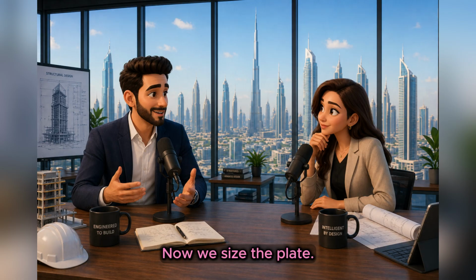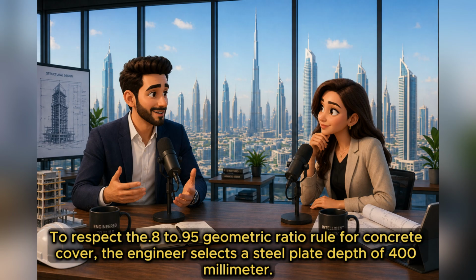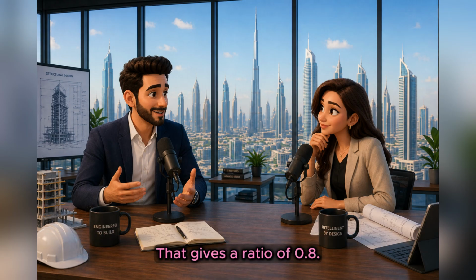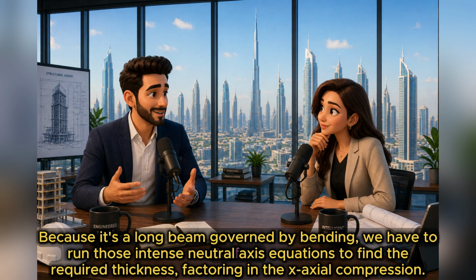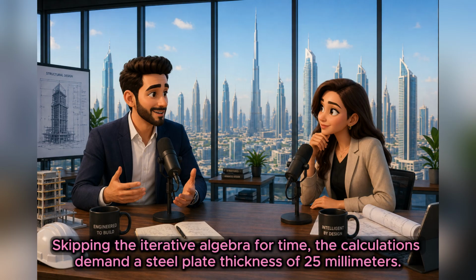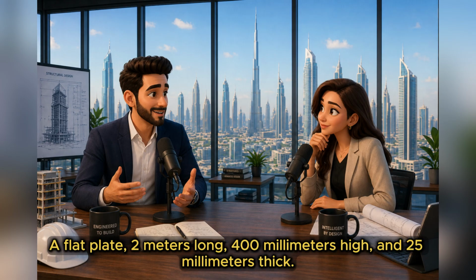Exactly. Now, we size the plate. The beam depth is 500 millimeters. To respect the 0.8 to 0.95 geometric ratio rule for concrete cover, the engineer selects a steel plate depth of 400 millimeters. That gives a ratio of 0.8. Perfect. Because it's a long beam governed by bending, we have to run those intense neutral axis equations to find the required thickness, factoring in the axial compression. Skipping the iterative algebra for time, the calculations demand a steel plate thickness of 25 millimeters. Right, so our core element is defined. A flat plate, 2 meters long, 400 millimeters high, and 25 millimeters thick.